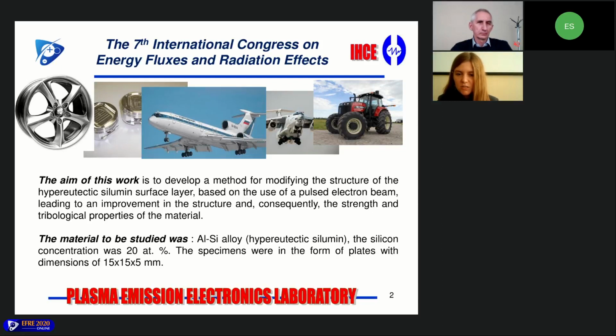So in our work, we use electron beam treatment, and electron beam treatment in optimum modes allows one to form a nanostructured surface layer in silumin and to greatly improve its physicochemical and strength properties, which is unattainable by conventional surface treatment.